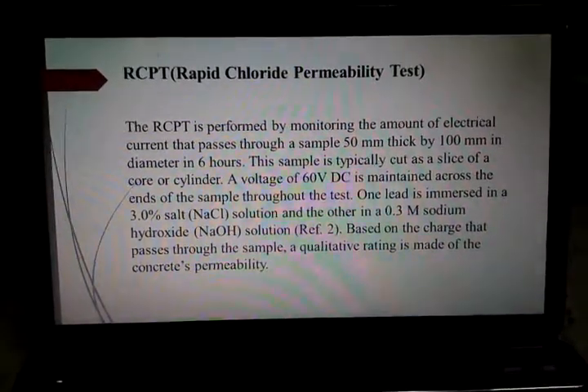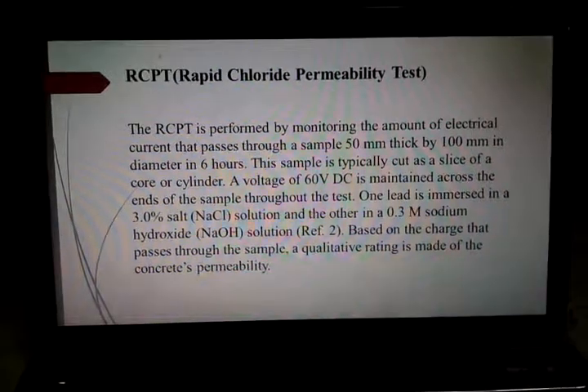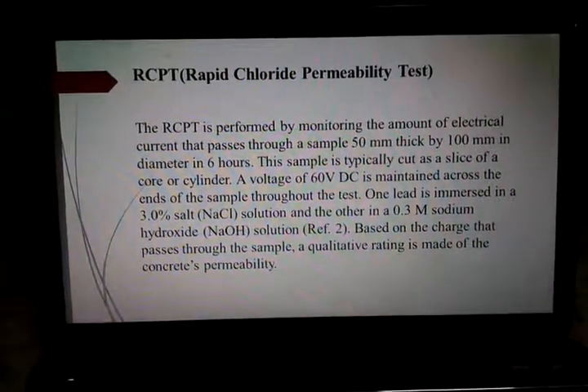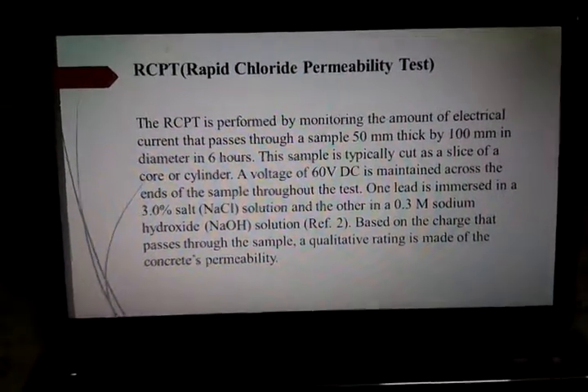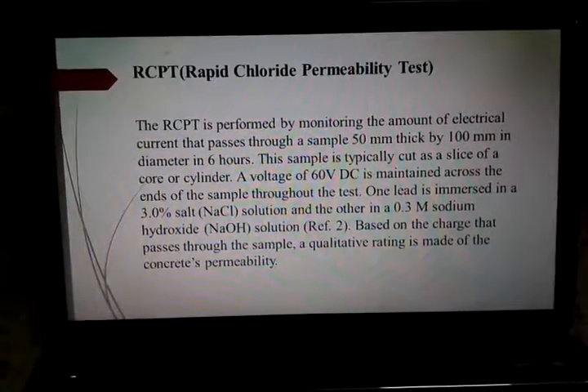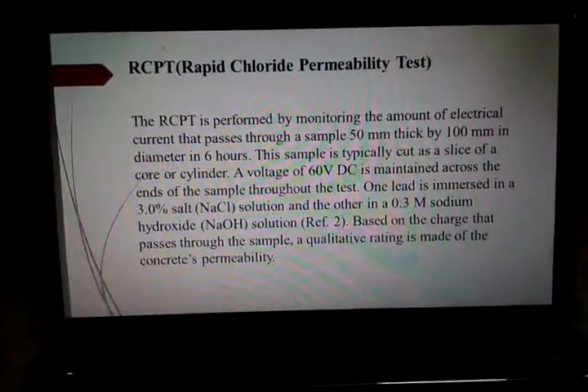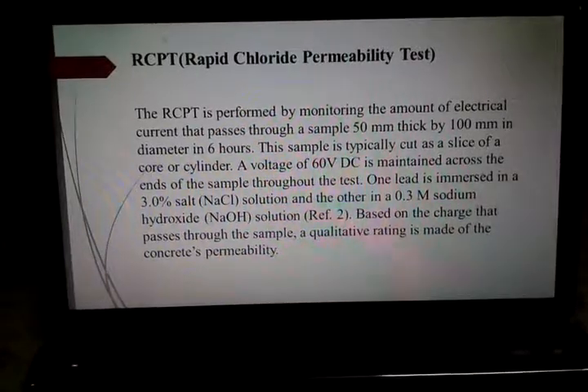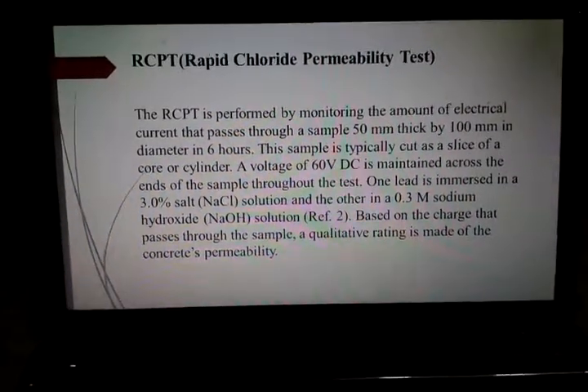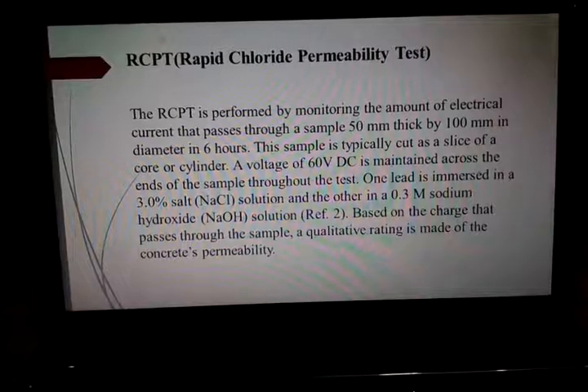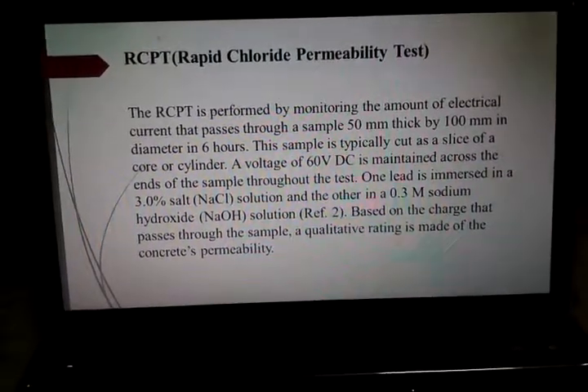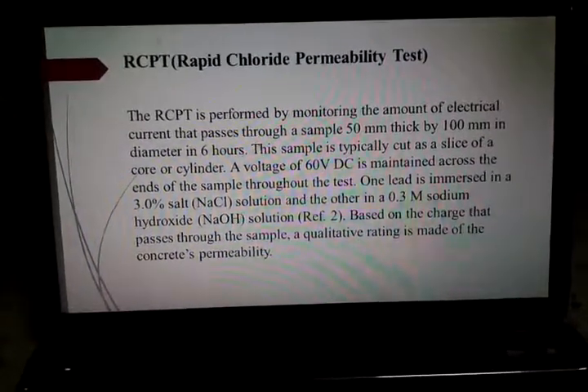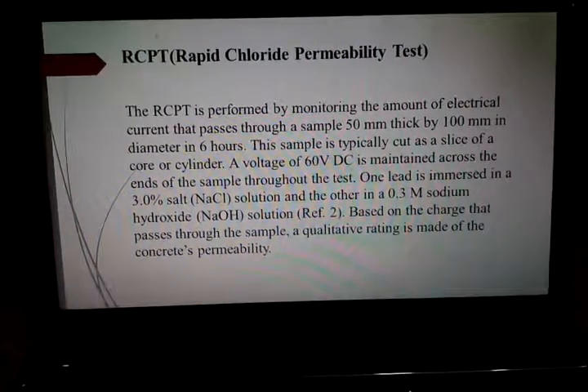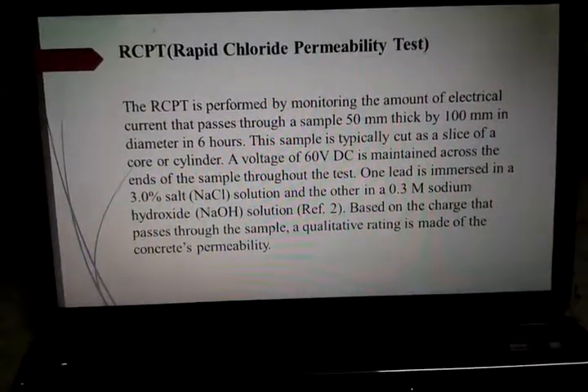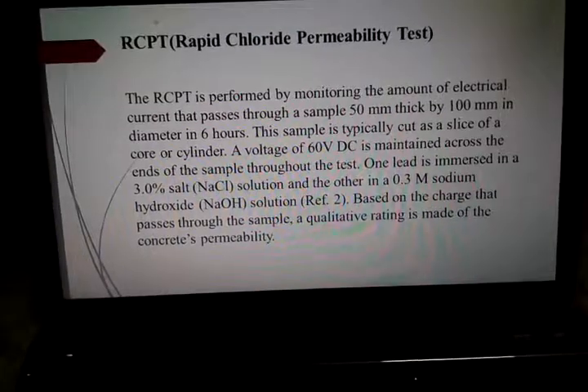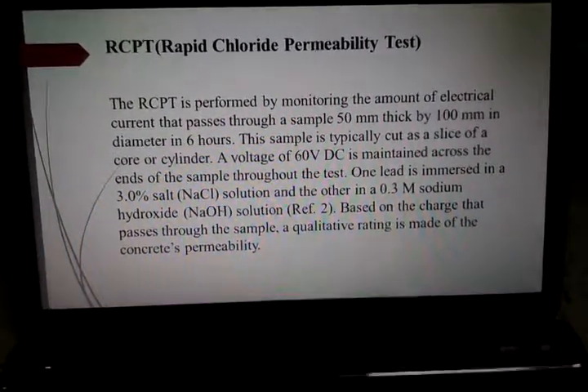RCPT, rapid chloride permeability test or penetration test. This is conforming to ASTM C1202. It is performed by monitoring the amount of electrical current passing through a sample of 50 mm thick by 100 mm in diameter in 6 hours. The sample is typically cut as a slice of core or a cylinder. The voltage of 60 volt DC is maintained across the ends of the sample throughout the test. One lead is immersed in a 3% NaCl solution and the other in 0.3 molar sodium hydroxide NaOH solution.